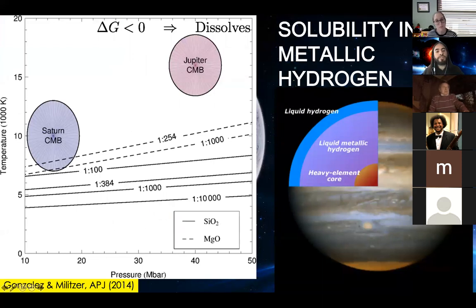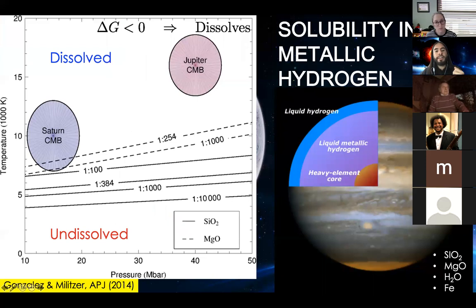So for the pressures and temperatures that we believe that Jupiter's core is, in particular the core mantle boundary here, and also Saturn's core mantle boundary, we find that this system is dissolved. That means the energy of the dissolved state is smaller than the energy of the undissolved state for any composition, for any concentration that you choose. And we did it not only for silica, but also for other minerals like MgO, ice, and iron. So we think that liquid metallic hydrogen is a very good solvent of any rock that you put there.